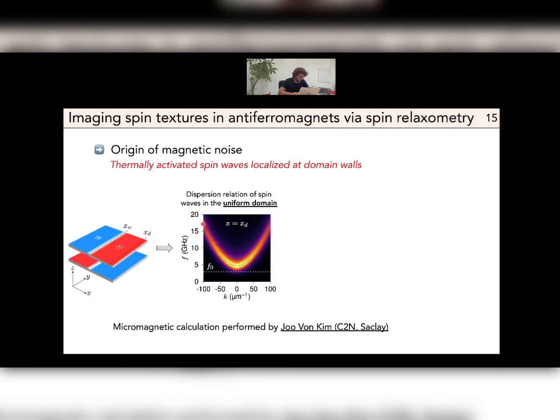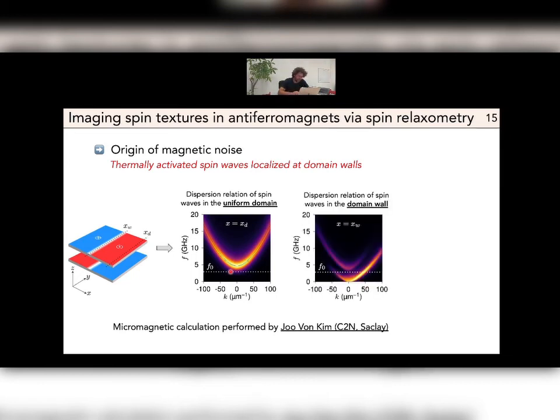In a uniform domain, this is the dispersion relation here, and what is interesting is that there is a gap in the dispersion relation that is essentially given by the anisotropy in the sample. If you plot the value of the electron spin resonance frequency of the NV defect, you can see that there are no magnons at this frequency, and as a result it's not possible to have magnetic noise at the electron spin resonance frequency. So although there are some magnons populated, they will not produce a noise that will be felt by the NV defect.